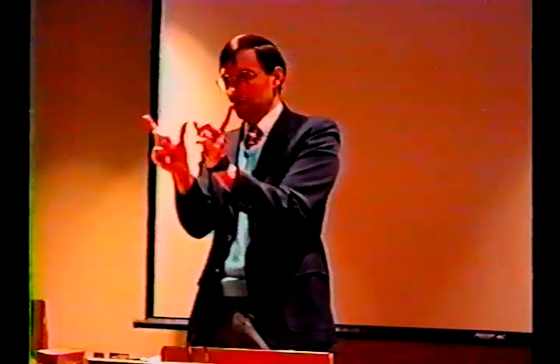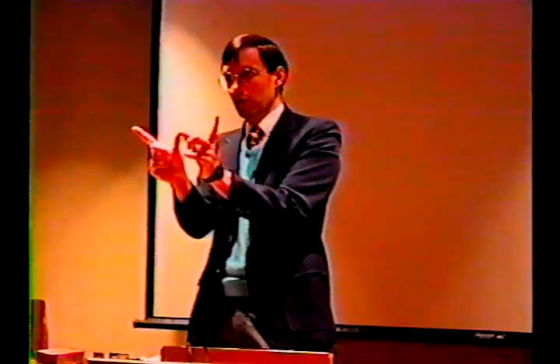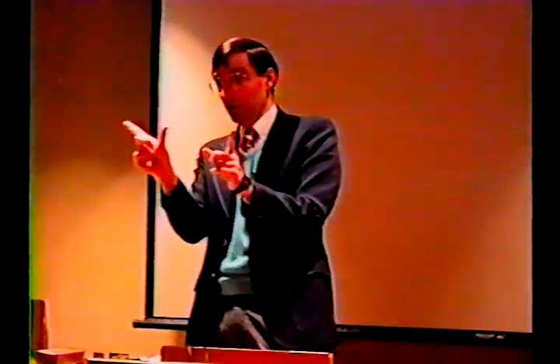What we try to do is we have these two wells of quartz. Microwaves can't get into glass, so it's a quartz tube. We put the metal carbonyl precursor in one well. We pull the vacuum from over here and absorb this onto a dehydrated zeolite. Try to make sure all the water's out of there to kill off the acidity, and we treat it with sodium vapor first. So the metal carbonyl comes over and absorbs into the pores. Lots of people believe that from infrared evidence and all. Maybe there's some on the surface. Maybe there's some inside. Maybe both.